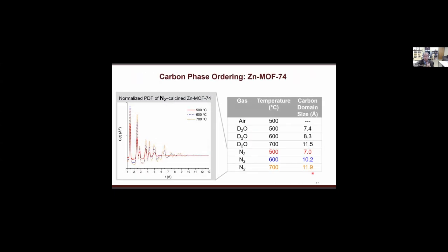The carbon phase, as you can tell from here, this is a zinc MOF-74. And then we did this in D2O at different temperatures, and nitrogen at different temperatures. Now we actually show the data for nitrogen calcined. As you can tell, when you go from low temperature to high temperature, the domain size becomes larger and larger.